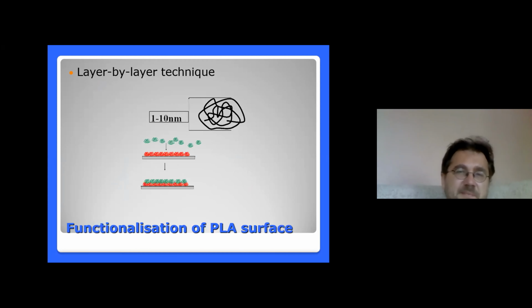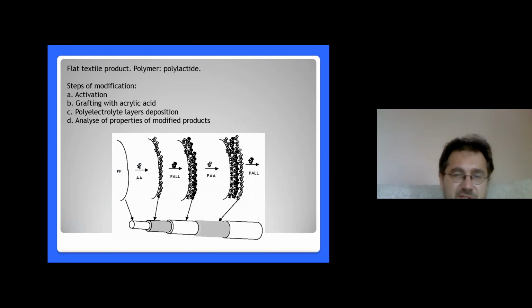And the last method which I would like to introduce is the layer-by-layer technique, which was proposed by Gero Decher about 25 years ago. He applied this method for mica, for metals, gold, silver, etc., but not for textiles. But we use this methodology for textiles. Of course, to apply this methodology, we need to have a charged surface. Polylactide is not charged, so we use grafting methods to introduce charge as a first layer. The source of charge was polyacrylic acid, and thanks to that, we create such a multi-layer structure to control the external layer of the material to a greater extent.